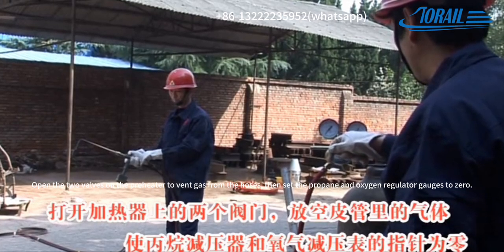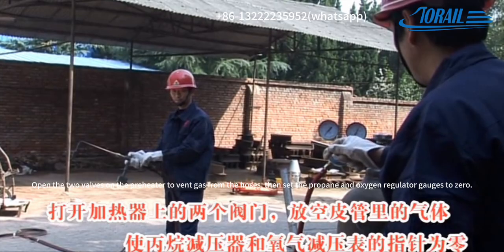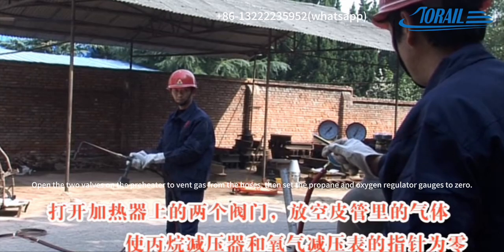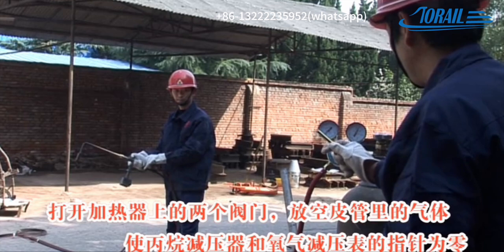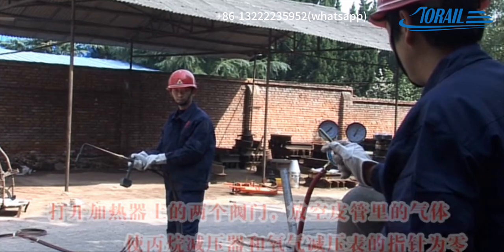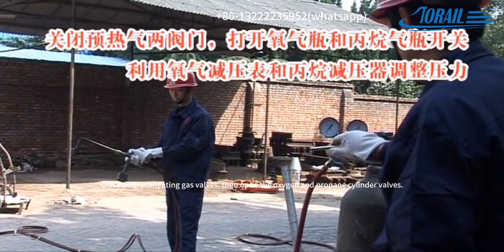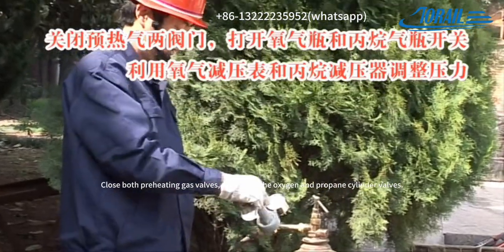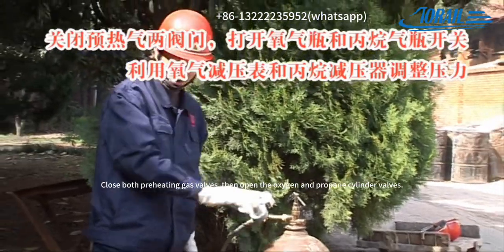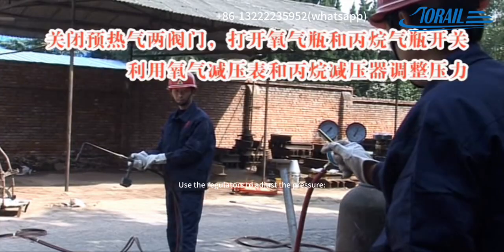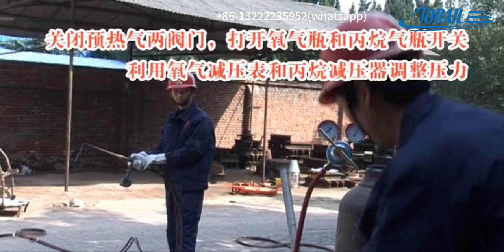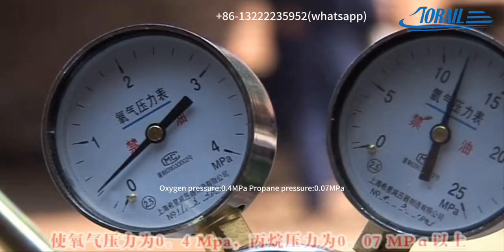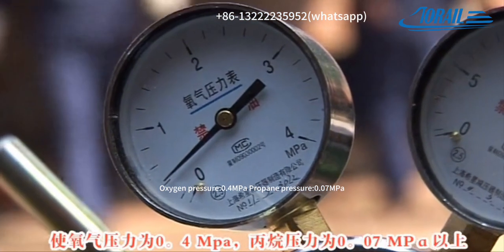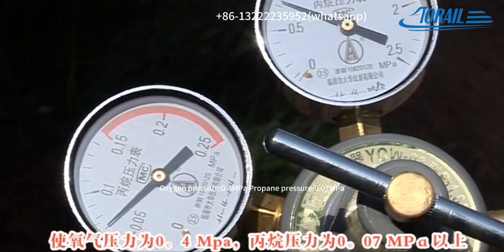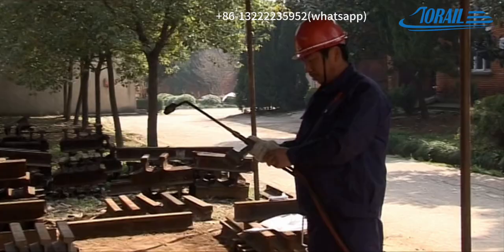Preheat. Open the 2 valves on the preheater to vent gas from the hoses. Then set the propane and oxygen regulator gauges to 0. Close both preheating gas valves, then open the oxygen and propane cylinder valves. Use the regulators to adjust the pressure. Oxygen pressure 0.4 megapascals. Propane pressure 0.07 megapascals.